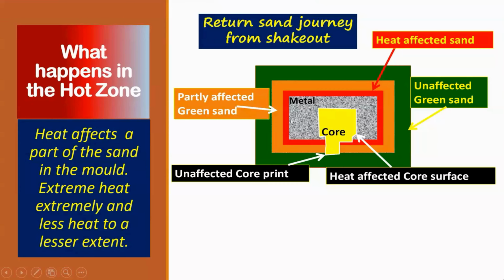Now, when you shake out the casting out of this mold, then the rest of the sand, whether it is fully heat affected or partly affected or not affected, all of them are going to get mixed up. The whole mold box without the casting is going to go through the grill during shakeout, and then at the bottom of the grill, you collect all of it on belt conveyors. The sand is extremely hot, humid area, a lot of steam is coming out, a lot of fumes come out, a lot of dust is generated, and one would not like to go near it at all. But this is the area in which you will see a lot of things happening. We'll talk about those aspects a short while from now.